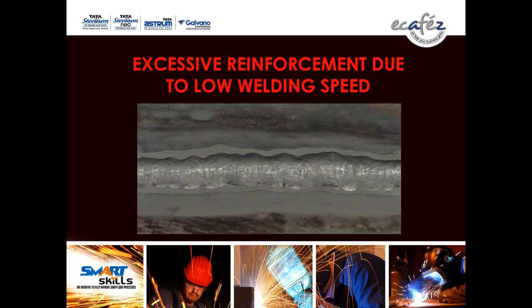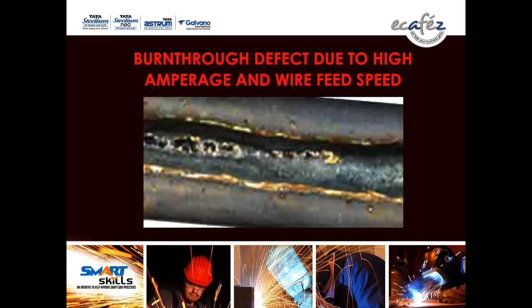Excessive reinforcement. This is due to very low welding speed in MIG process. So excessively low welding speed will give you a joint like this. Burn through defect due to high amperage and wire feed speed. If you use MIG process with excessive high current, then you can see this type of burn through or melt through in your butt joint, in the underside of the joint.